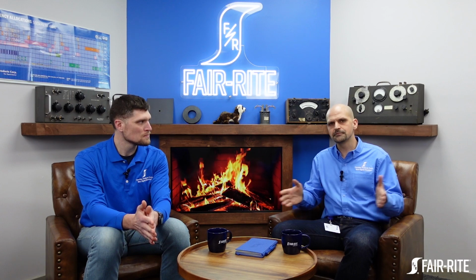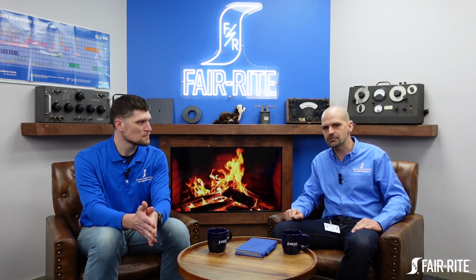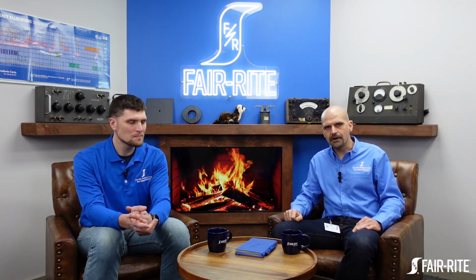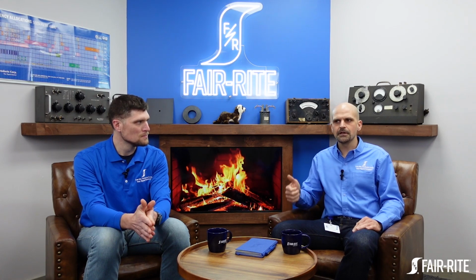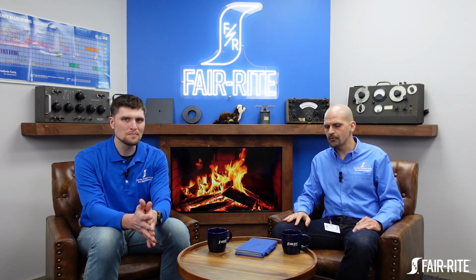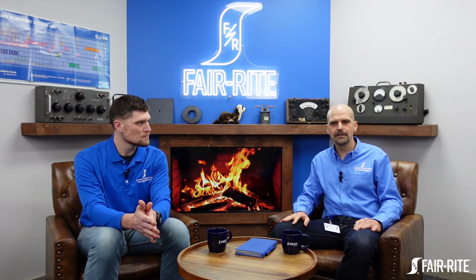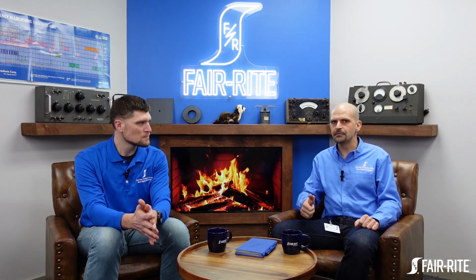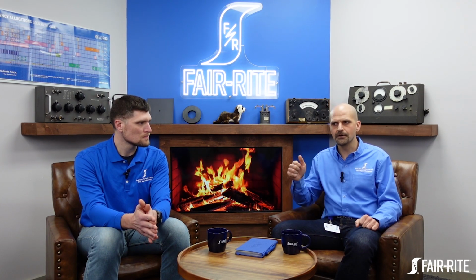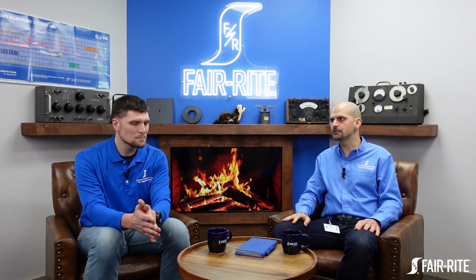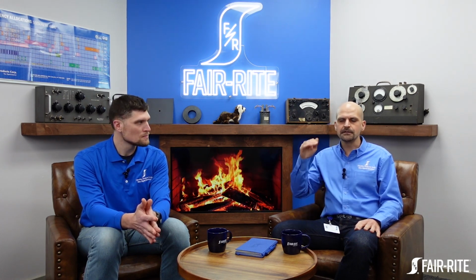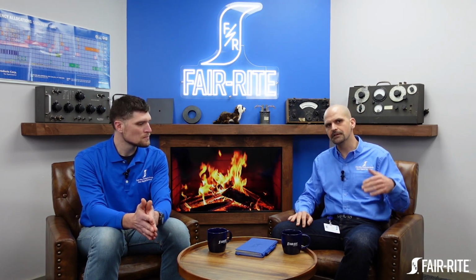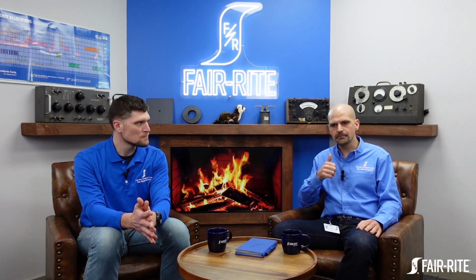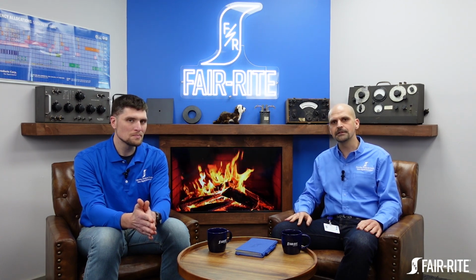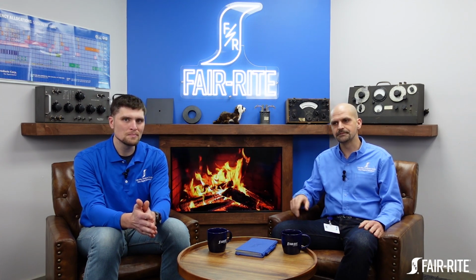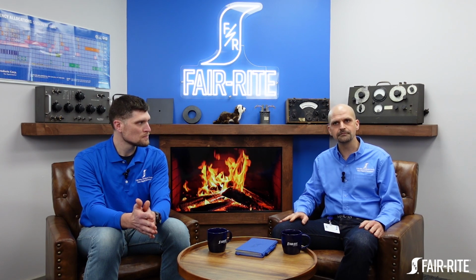Just for example, if you have an application with an ambient temperature of 85 degrees, which is a typical value, and you have a self-heating of your winding of, I don't know, 30 degrees, then you can assume that your core might be around 100 Celsius under normal operating conditions. And at 100 Celsius, you will see a different inductance value, different permeability, different saturation characteristic. And that is the third topic that we just arrived at.